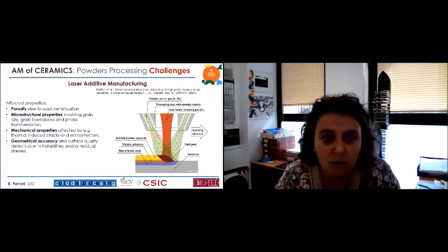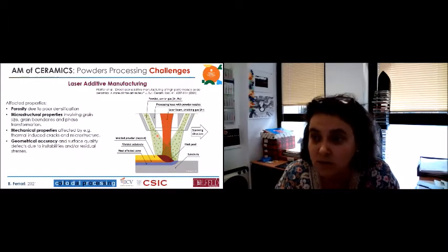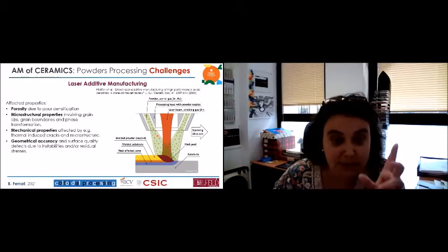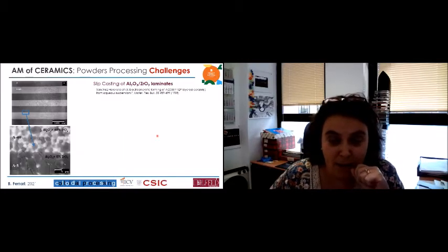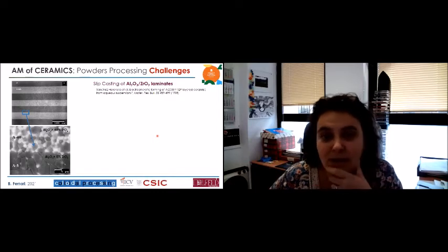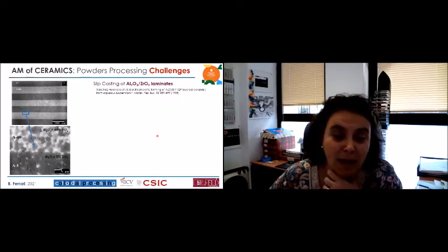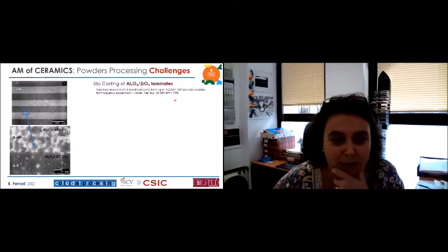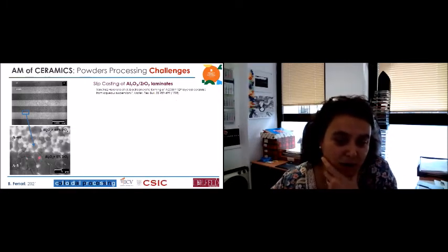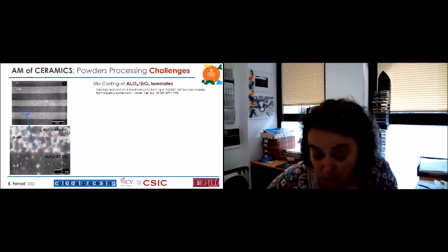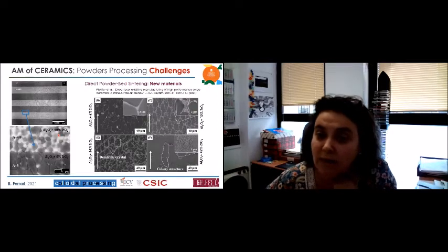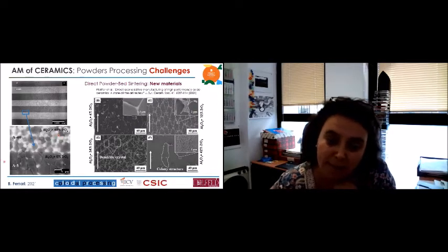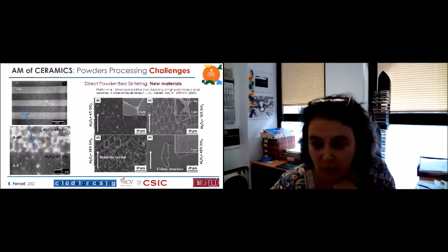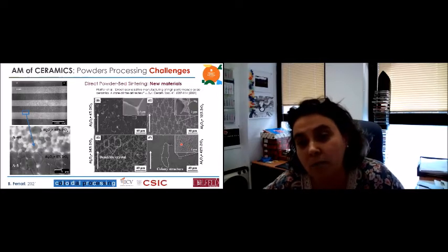So with all these problems, you are going to ask me why we need to research this process. This is very easy to answer. If I show you a conventional slip casting material made of alumina zirconia, this publication is from '98, right? You can see here all your alumina grains and here all your zirconia grains mixed together in a laminate. And if you go to the direct laser additive manufacturing, you are going to see exactly the same material, 40% zirconia here, but in a completely different microstructure.